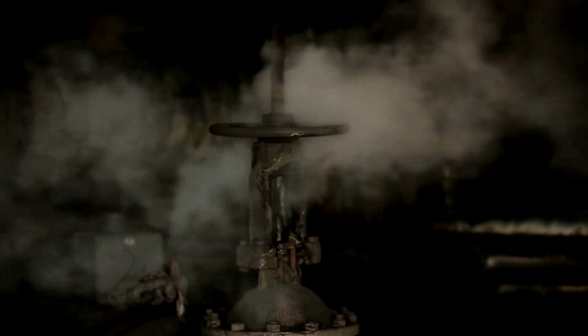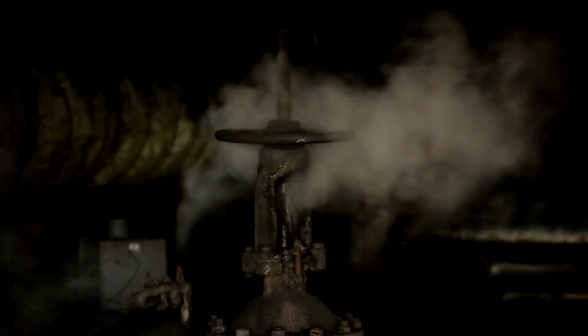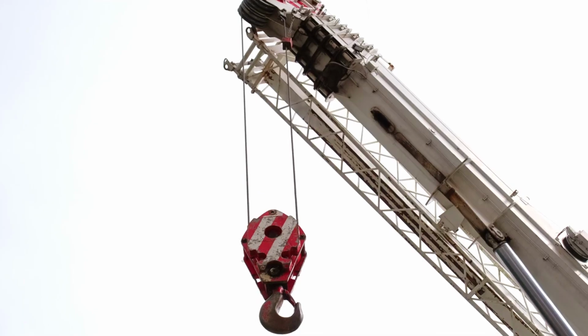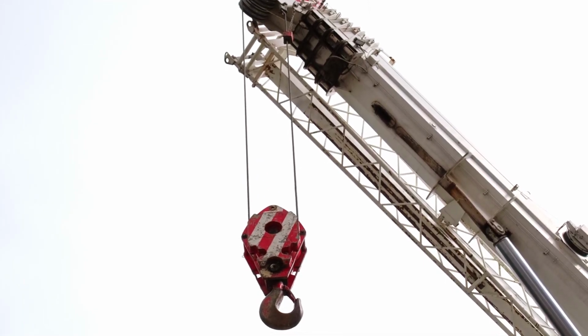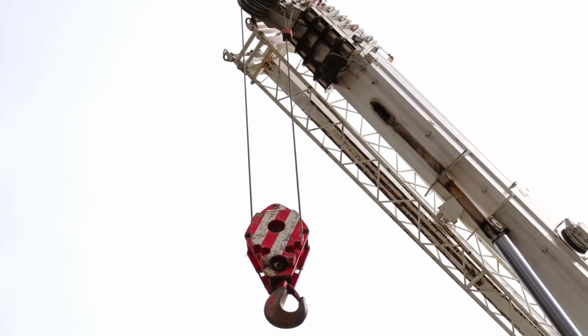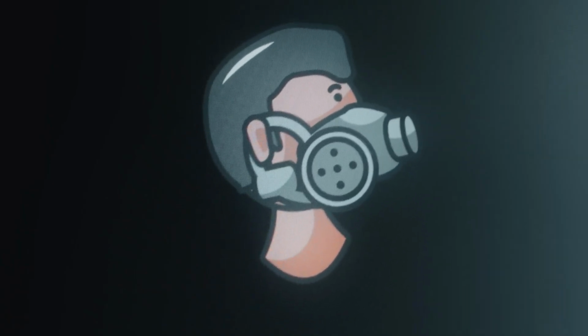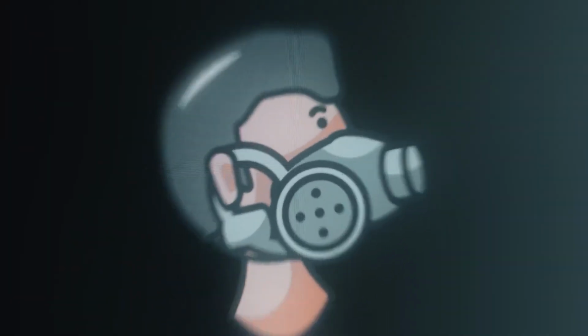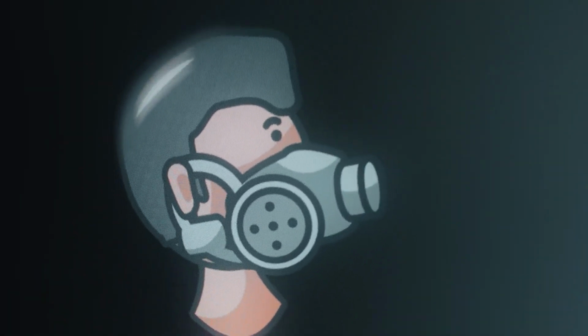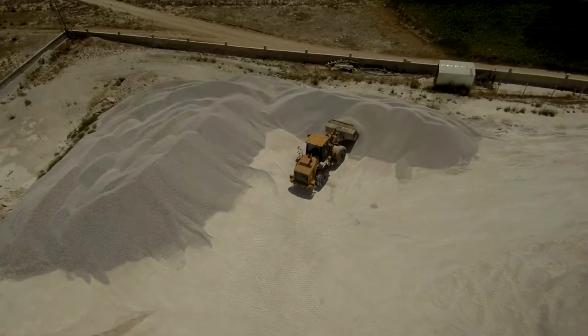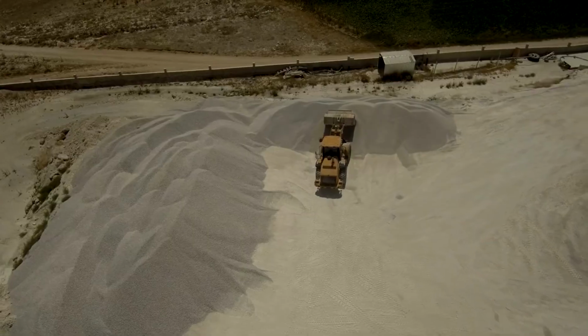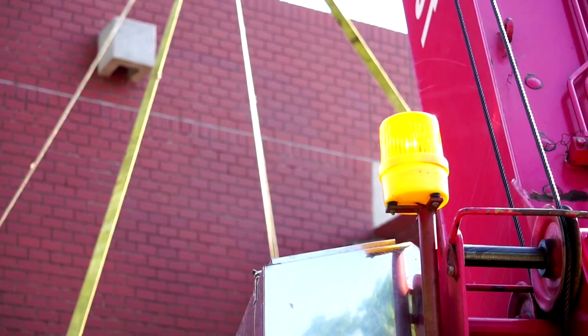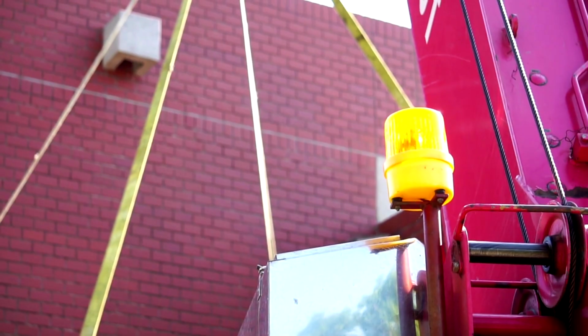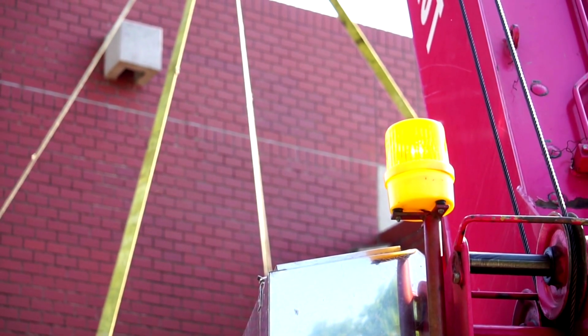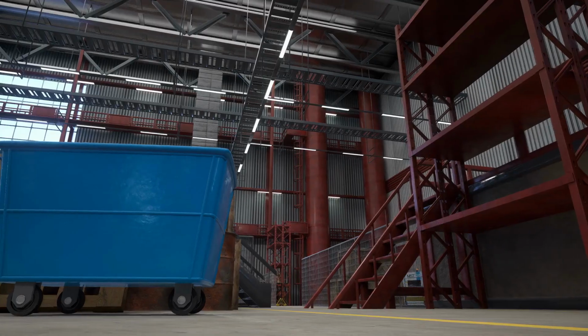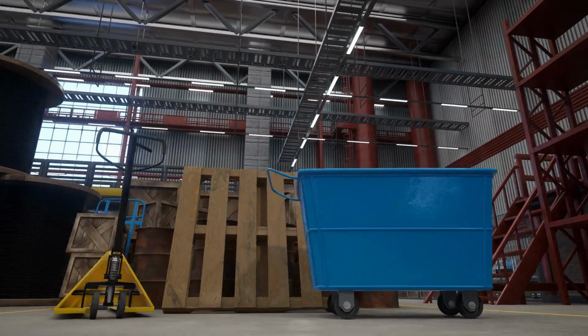When a ladle drops, the event is over in less than 2 seconds. There is no time to shout a warning, no time to run. The ladle falls from a height of 20 to 40 feet, depending on crane position. Gravity accelerates it instantly. By the time it reaches the floor, it is traveling at more than 30 miles per hour. The impact is catastrophic. The ladle does not land intact. The refractory lining shatters on impact. The steel shell ruptures. Molten metal erupts outward in all directions.